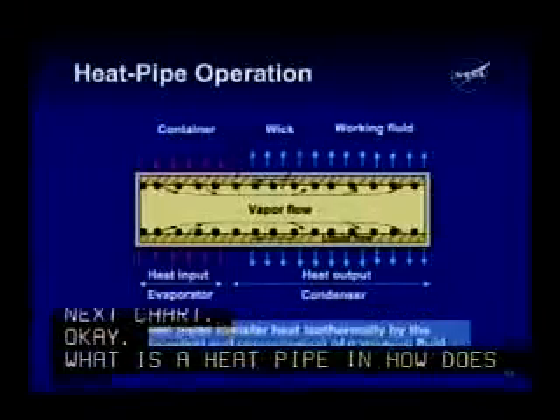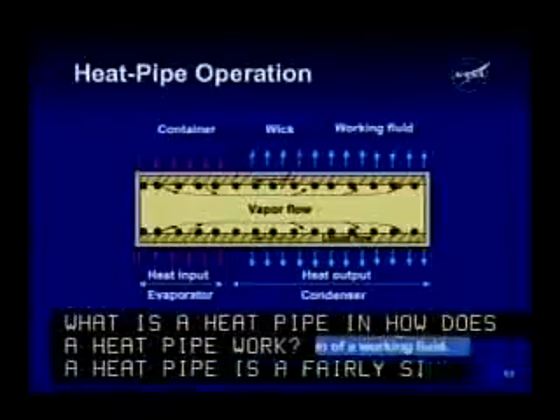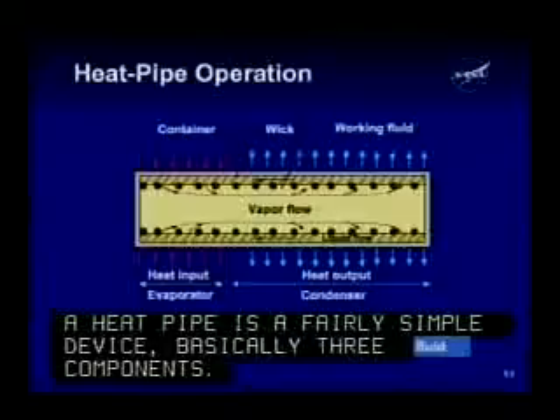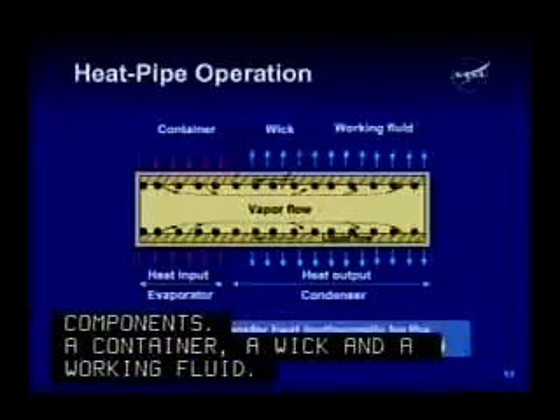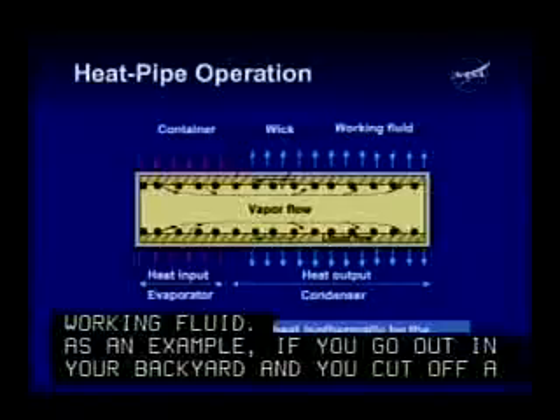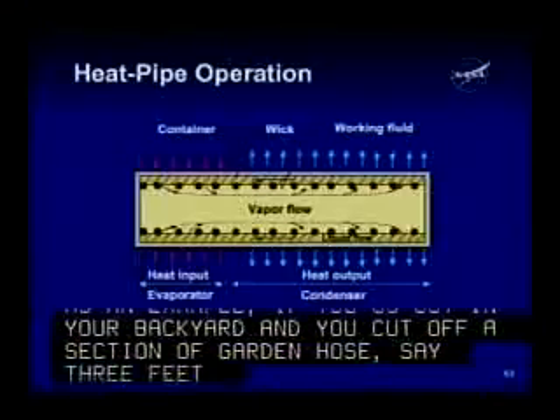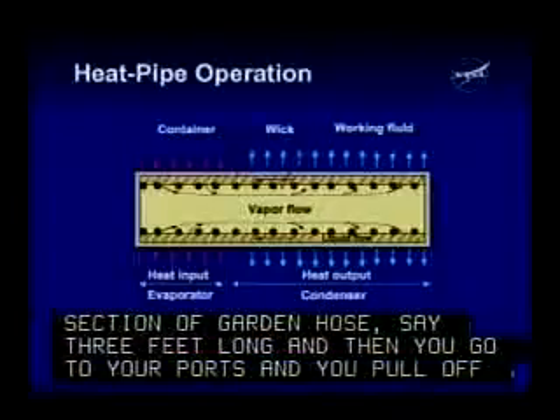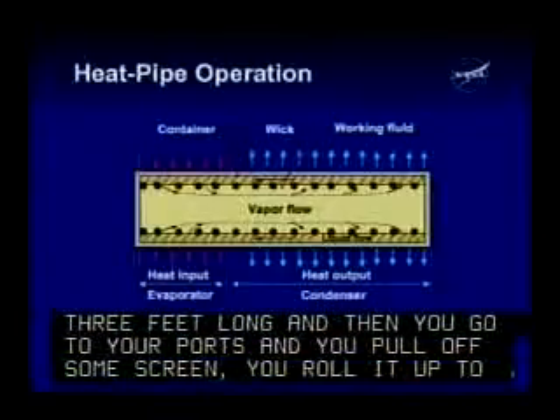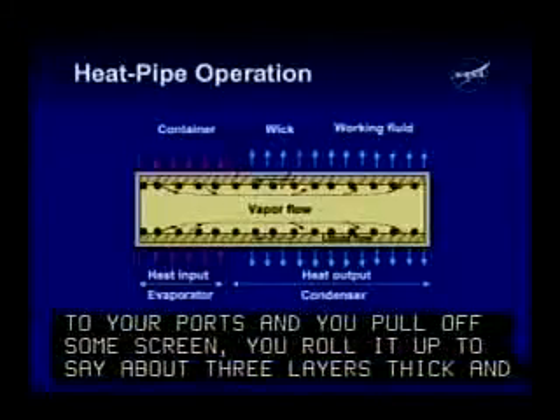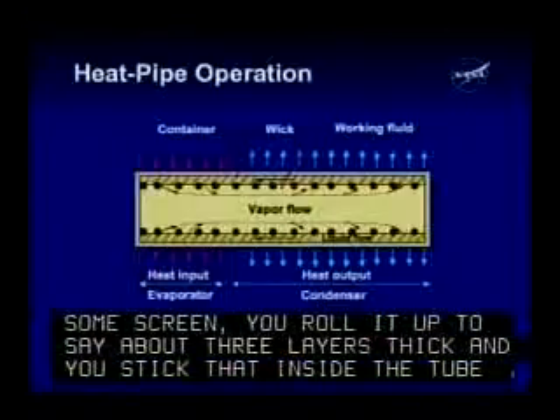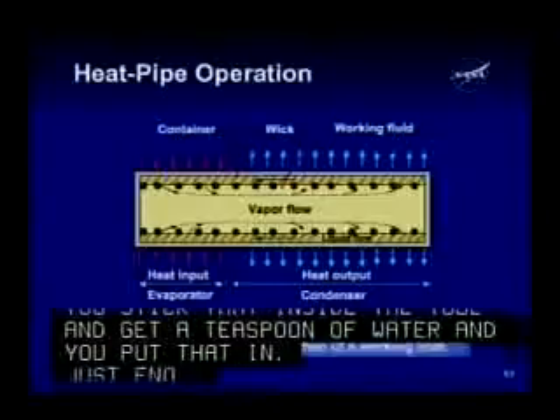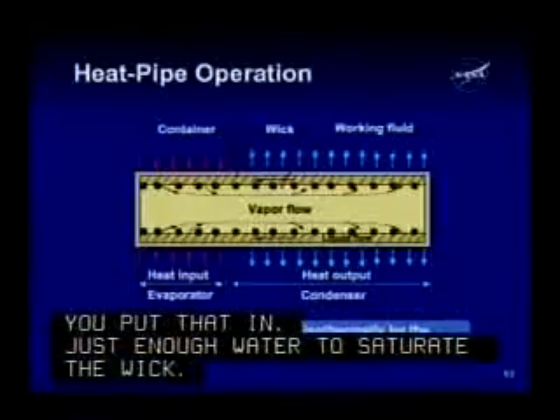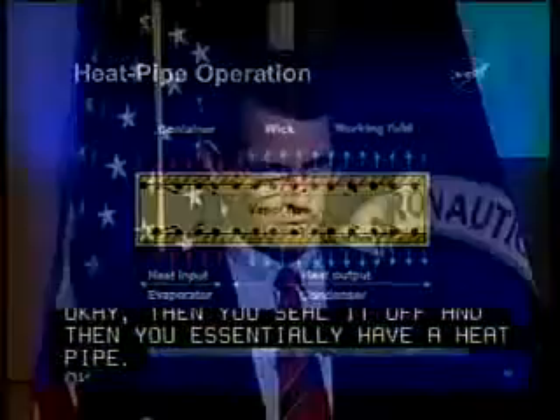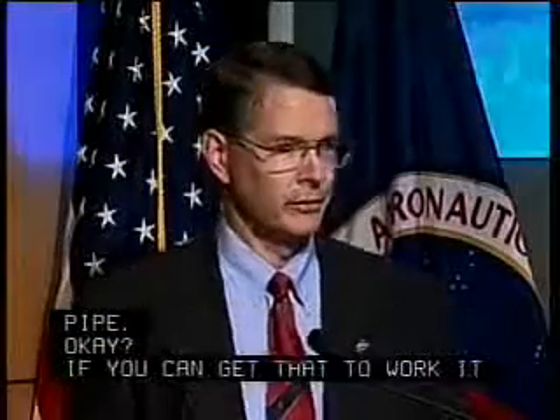How does a heat pipe work? A heat pipe is a fairly simple device, basically three components: a container, a wick, and a working fluid. As an example, if you go out in your backyard and you cut off a section of garden hose, say 3 feet long, then you go to your porch and you pull off some screen, you roll it up to, say, about 3 layers thick, and you just stick that inside of the tube, and then you get, say, a teaspoon of water, just enough water to saturate the wick, then you pull a vacuum on it, you seal it off, now you essentially have a heat pipe. If you can get that to work, it would operate at, say, a few hundred degrees.